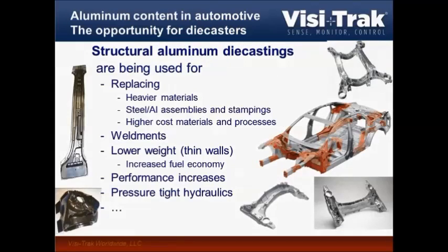and so on. All these structural castings are used for replacing typically heavier materials, often steel, but also aluminum assemblies, often stampings, or any high-cost materials and processes. Very often weldments, and they're used to get lower weight because you can get thinner walls with die casting than with any other casting process, which will lead to increased fuel economy. You get performance increases. That's especially true when it comes to fatigue because the high freezing rate and the skin effect of die castings can hardly be beat by other casting processes. It's also used for pressure-tight hydraulics and other components that we will see in just a minute.